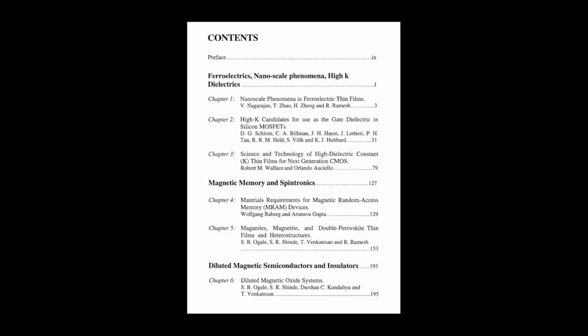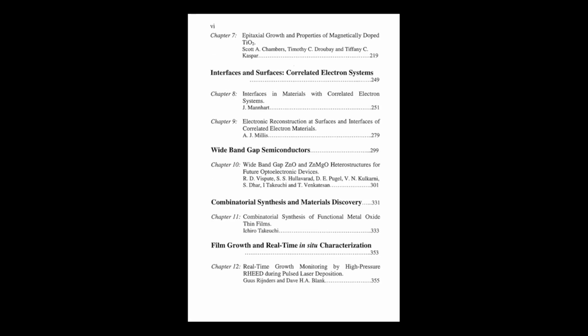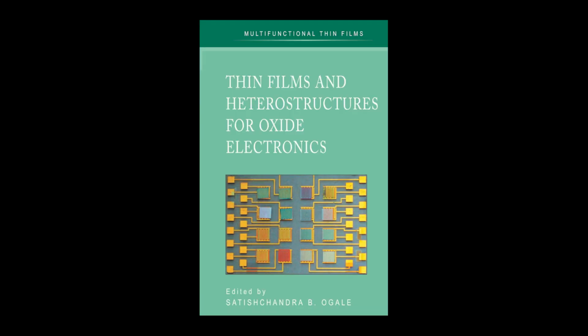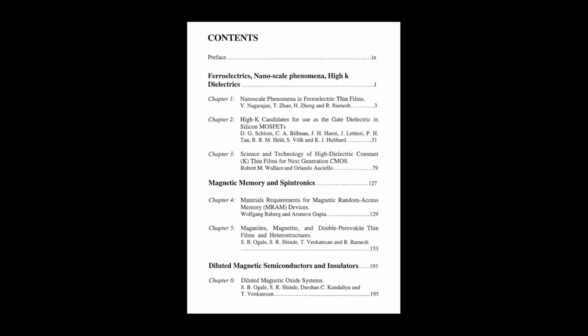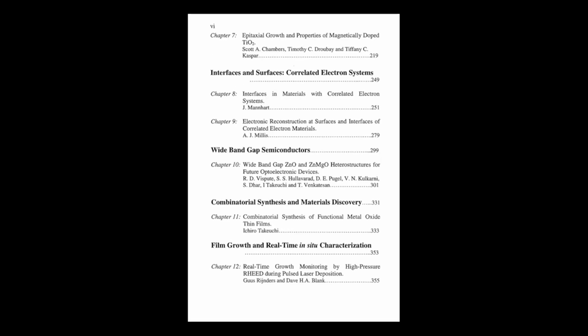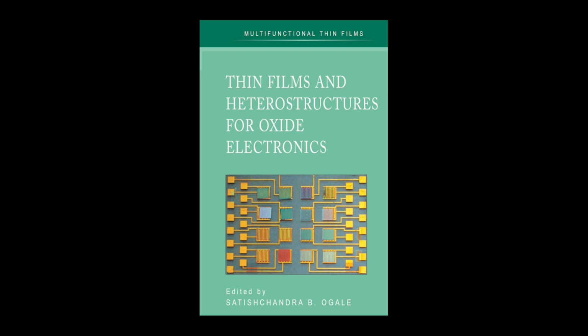Okay, so after all this debate, clusters, AHE confusion, F centers, what's the final verdict on DMOs from this period? Is there a consensus? I think the consensus that emerged, as reflected in the source, is that achieving reliable, intrinsic DMO behavior is incredibly sensitive to the choice of dopant and the growth conditions. Uniformity is absolutely king. Some dopants work better than others. It seems so. Cobalt and iron seem very prone to clustering, forming those secondary metallic phases, which makes interpreting the results incredibly difficult. The source actually points to chromium, Cr, as perhaps the best-behaved dopant in TiO2 studied up to that point.